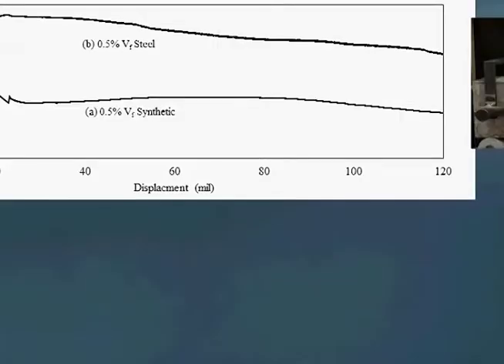So here is the thing which is important. Fibers, synthetic fibers or steel fibers, how do they perform? These three graphs show no fiber, then 0.5% volume fraction synthetic fiber, and then 0.5% volume fraction steel fibers. Steel fibers perform better than the synthetic fiber.